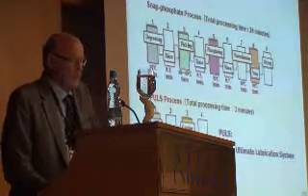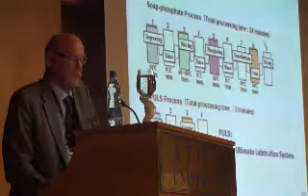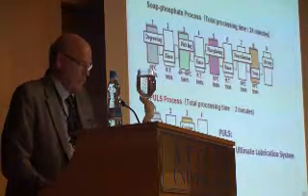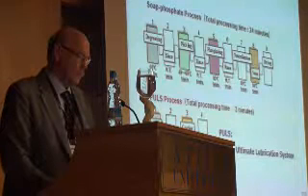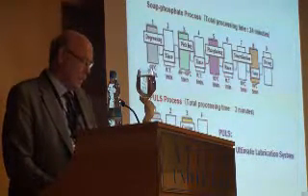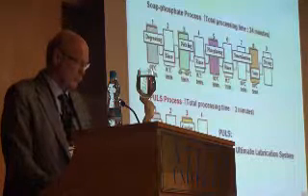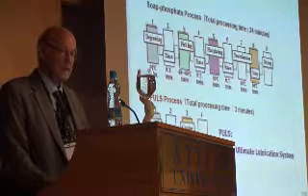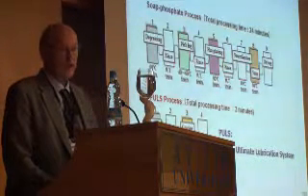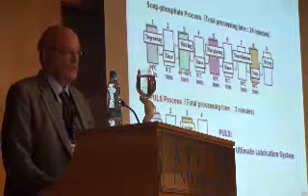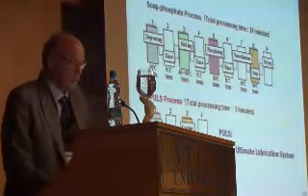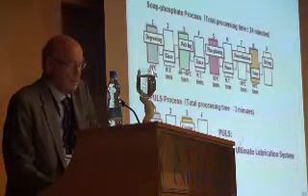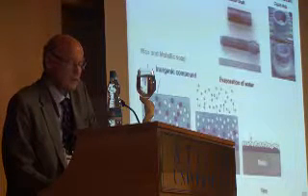In normal phosphate coating and soap lubrication, you take 24 minutes to coat, and it has to be offline. In the new process with Pulse, you descale the workpieces by shot blasting, you heat them, you coat them at 40 to 60 degrees for 1 second, and then you dry them and then you forge. And you could do it in process. So it's a total of 3 minutes to coat them, and Nippon Parkerizing claims it to be very efficient.